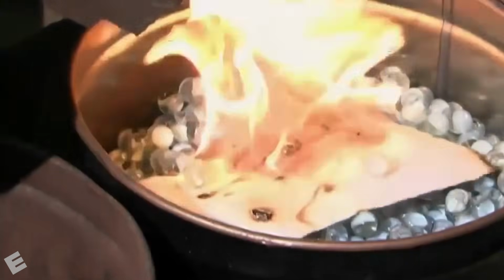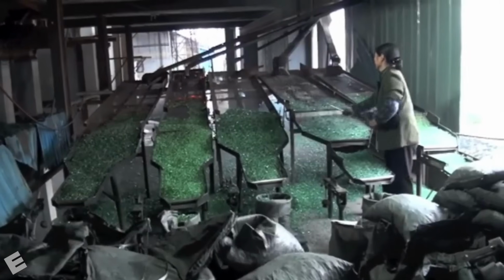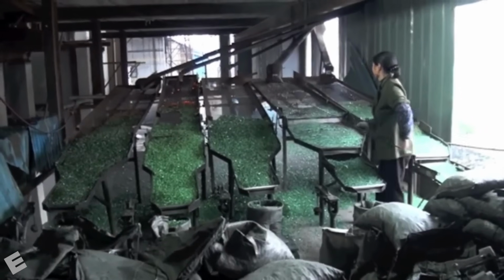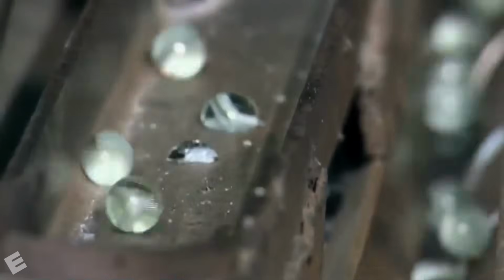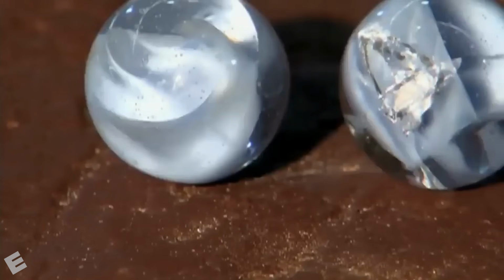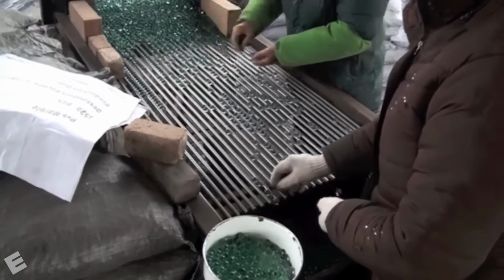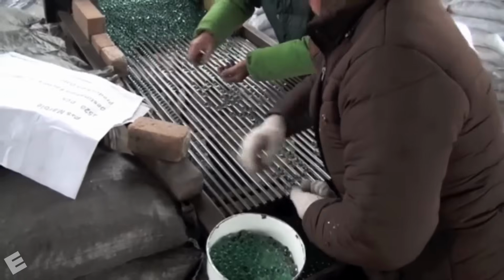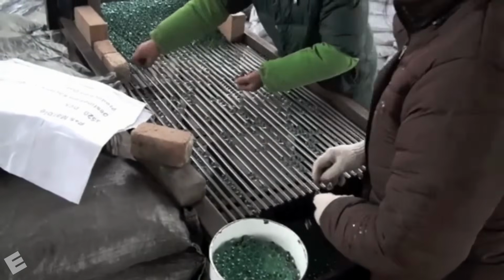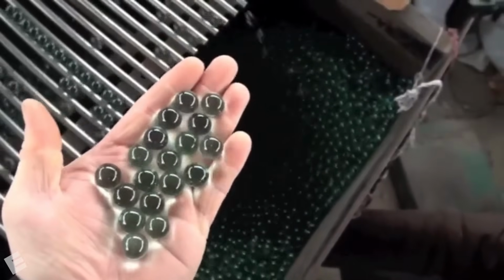Complete cooling takes approximately 24 hours and must happen slowly from the outside toward the center. If the marbles cooled too quickly, the interior and exterior would contract at different rates. This could create stress and cause the glass to crack or shatter. Slow cooling allows the temperature to equalize and makes the finished marble stronger.